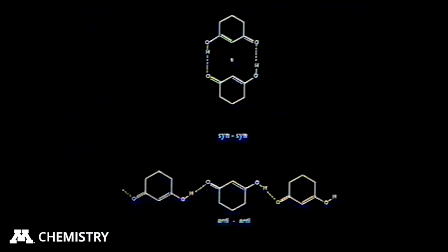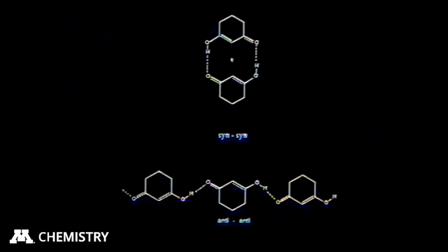So first let's look at the syn hydrogen bond pattern. It looks like I'm putting 2 molecules together like this. In fact, this hydrogen here is sterically interacting with that hydrogen. What happens instead of forming a dimer is it just slips a little bit, and it forms a helical chain, which in projection looks like that dimer. And dimedone crystallizes in this pattern, and dimedone is the compound that has 2 methyl groups there. So that pattern is known to exist. This pattern here is the anti-anti form, and we formed that exact pattern by crystallizing that molecule out of THF.